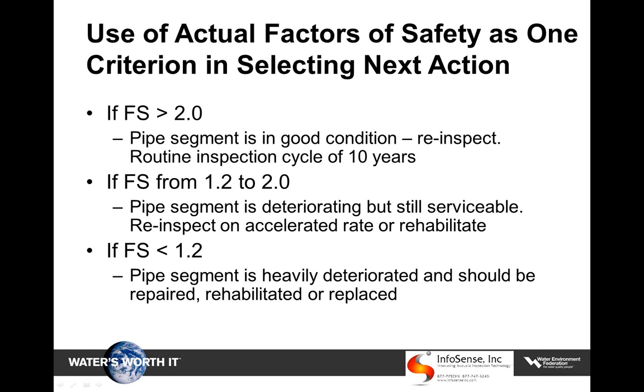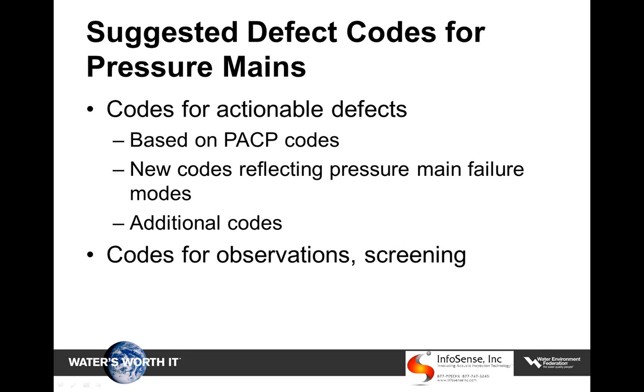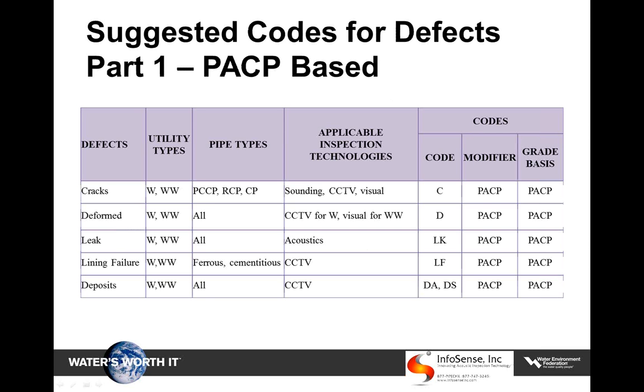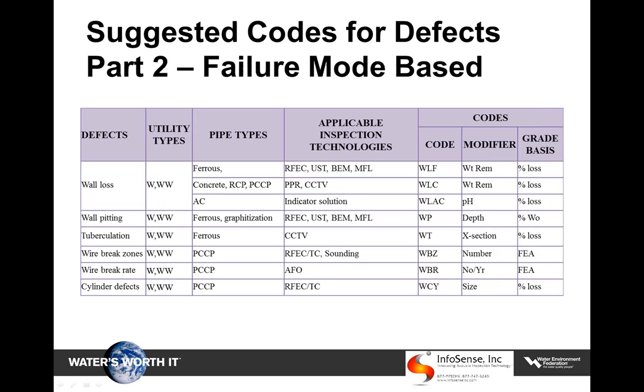So the next step was to develop a type of selection tool, and for that we are developing some very preliminary ideas of defect codes for pressure mains, starting with actionable defects and then progressing to observations and screening, things that we can use to actually make decisions on what to do for each of these defects. Obviously, we started with the PACP codes. We had about 5 that made the transition that were applicable to pressure mains. There are some more out there, but these are the 5 basic ones. Cracks, deformations, leaks, lining failures, these are all fairly common to both gravity and pressure pipes. And for these, we use the same codes, same modifiers as PACP, and same severity grades from Appendix D in your PACP manual. To those, we've added defect codes that are more based on the failure modes of pressure mains.